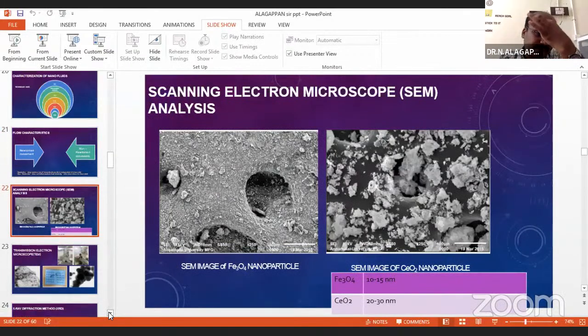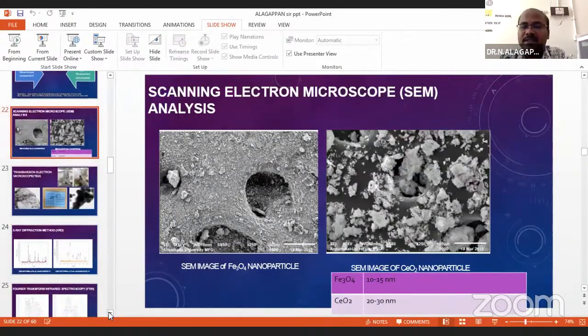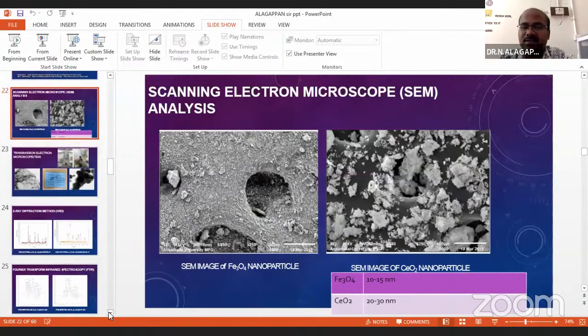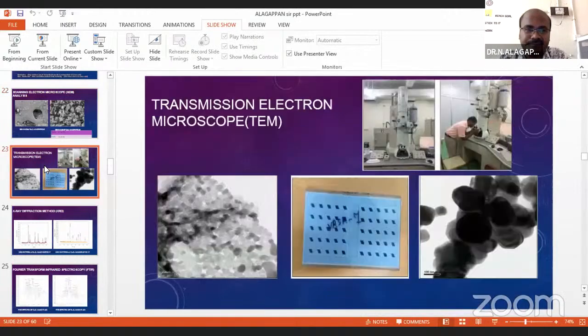So we have done SEM analysis for Fe3O4 and CeO2. In the SEM analysis, we can know the size of the nanoparticles. We have selected a size of 10 to 15 nanometer for Fe3O4, and for cerium oxide, 20 to 30 nanometer, which we can know only by means of SEM analysis. Next slide, sir. In the transmission electron microscope, we know the shape of the nanoparticles. For example, cerium oxide is crystalline in shape, and this Fe3O4 is amorphous, which means shapeless. Next slide, sir.